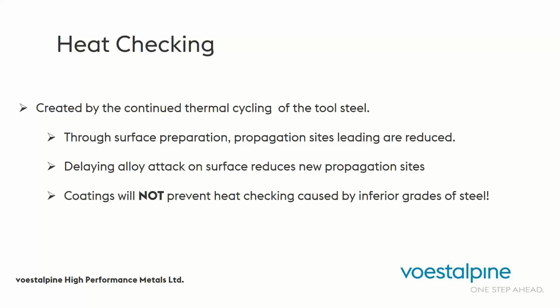Picture peaks and valleys, very sharp peaks, and coating being at 5 micron, it will not fill in the peaks and valleys of the surface. So what happens? You're coating a very, very minute, very sharp little peak. After a few hundred shots of a high velocity abrasive alloy, those peaks do bend and they break off, and that exposes coating underneath it. And it exposes steel underneath the coating.